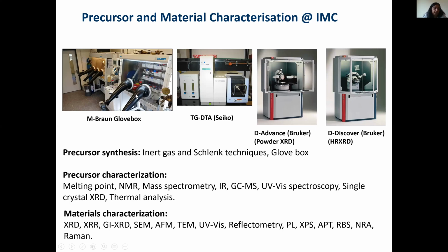Also, you can sort of avoid air or moisture. Then we characterize them with different analytical tools. You see NMR, mass spec, UV visible spectroscopy, single crystal X-ray diffraction, and also looking at thermal properties, because it's one of the important figures of merit for characterizing a precursor.